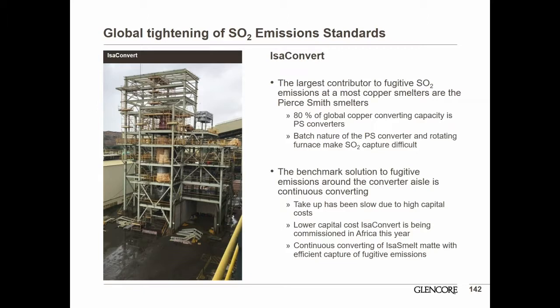The main issue in most copper smelters these days is emissions around the Pearce-Smith converters. So Pearce-Smith converting accounts for about 80% of converting worldwide. And because the Pearce-Smith converter is a rotating furnace, it's extremely difficult to seal around the port of the furnace. While we have seen some very good advances in hood technology and capture technology over the recent decade, it's still not sufficient to be able to capture the SO2 to the levels that we can see financing organisations globally moving to. So there is a need for a new converting technology.